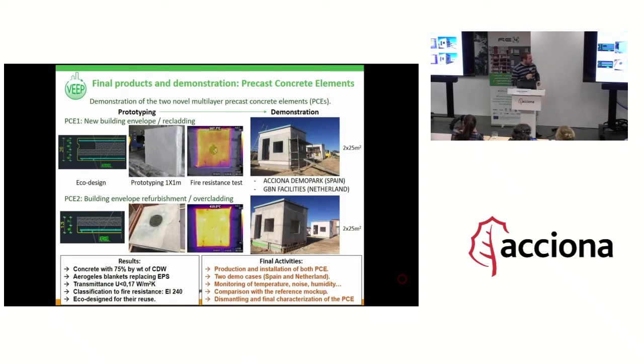The PCE1 is a multi-layer element with an external and internal recycled concrete layer, and an internal insulation layer that replaces the conventional EPS material with the new aerogel blanket. The second one is also multi-layer, but it is only composed of an external concrete layer and an internal aerogel layer. In this case, the concrete layer was made with lightweight concrete in order to improve the thermal properties and reduce the weight of the pieces.